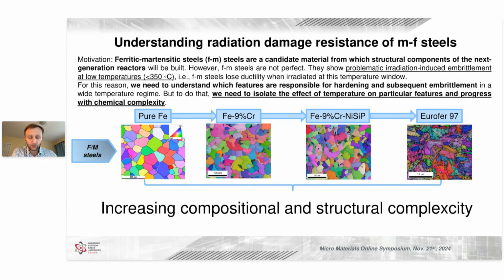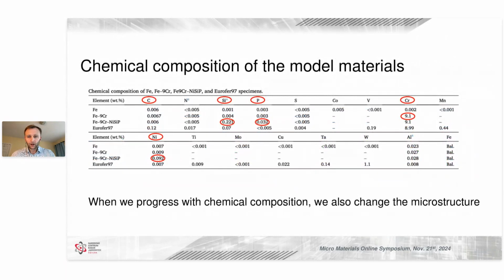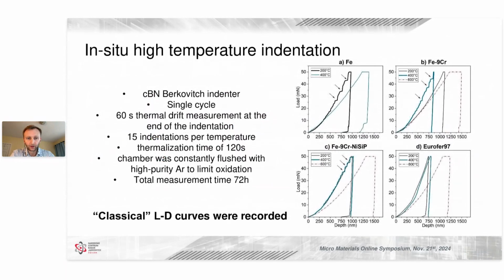And by progressing between those model materials, we increase compositional and structural complexity, which allows us to isolate the responsible mechanisms of hardening. It is very important to pay attention to the chemical composition between the samples we tested, as the only elements which changed are carbon, solute atoms like silicon, phosphorus, and nickel, as well as chromium. I will relate to this slide a little bit later.